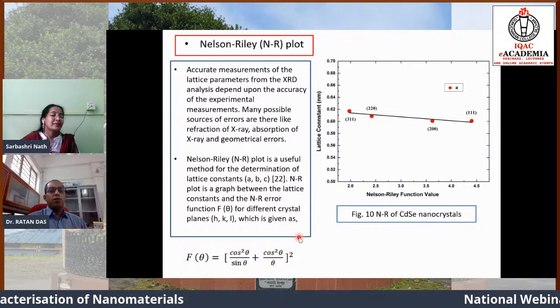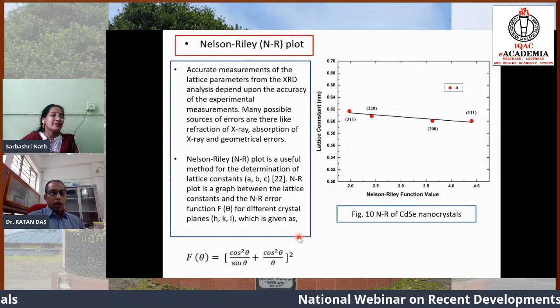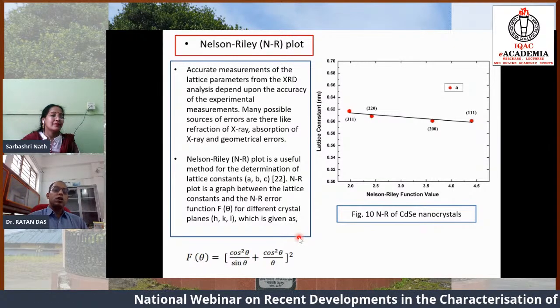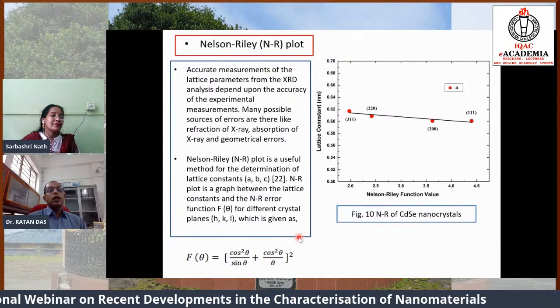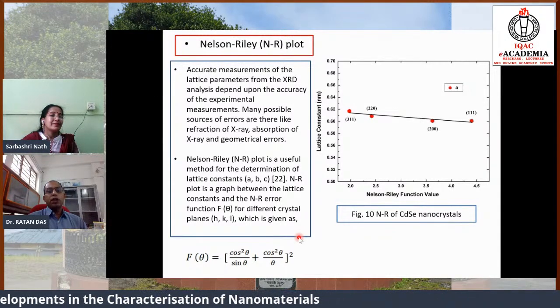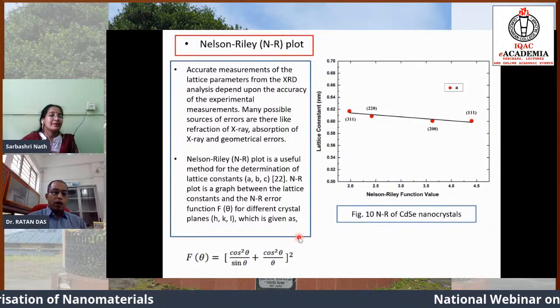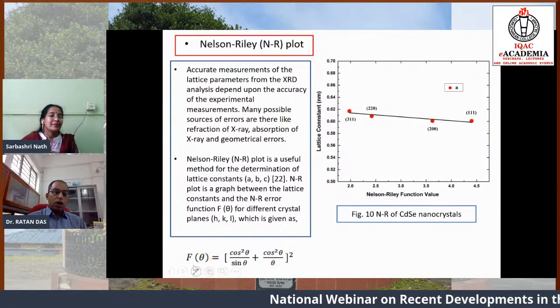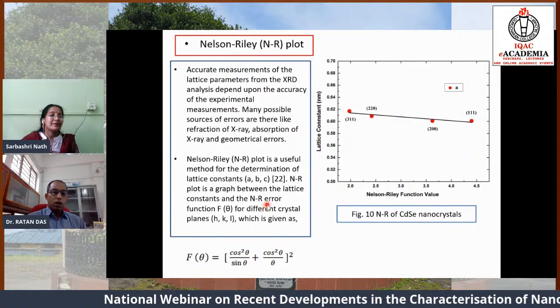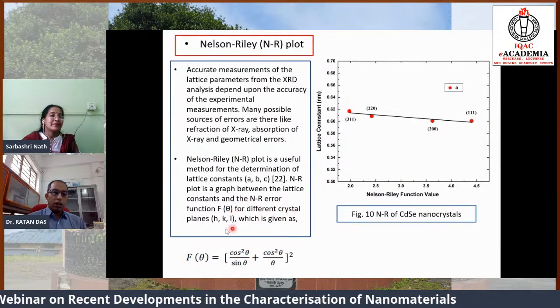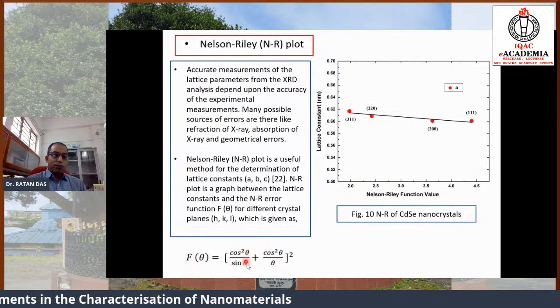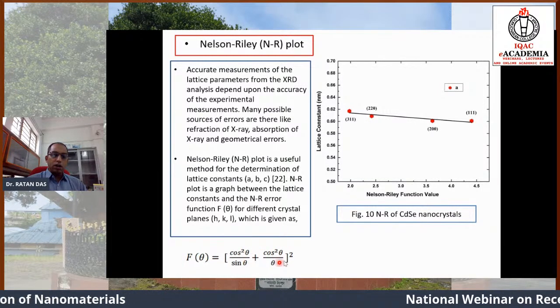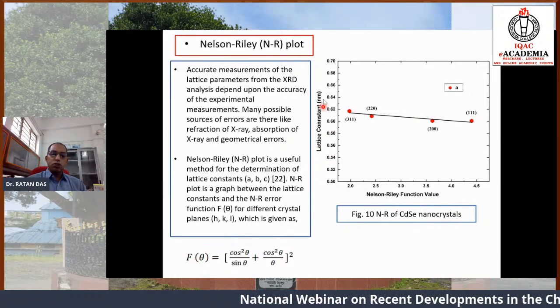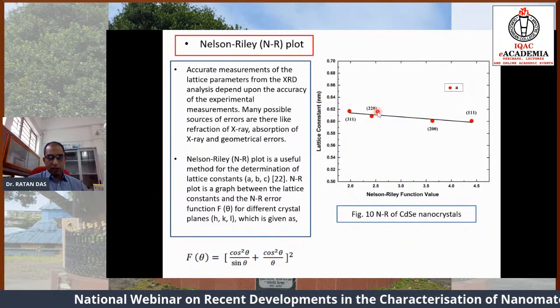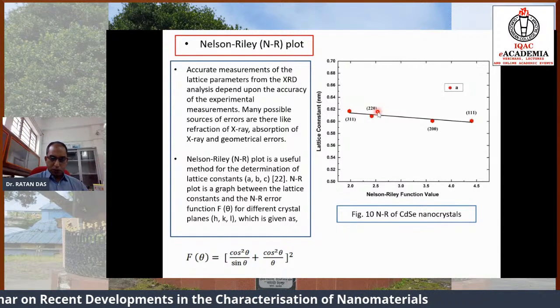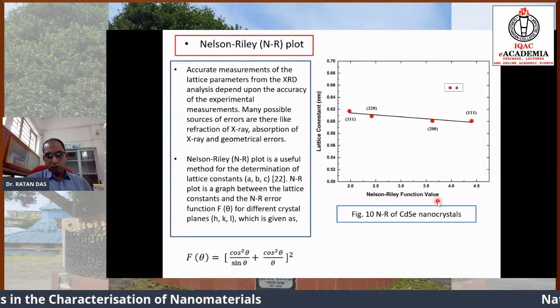That lattice constant can be obtained from the Nelson-Riley plot. In the Nelson-Riley plot, it is an errorless method of obtaining the lattice constant, where we use a particular error function, the Nelson-Riley error function f(theta), which relates to theta. We obtain the lattice constant value from Bragg's formula and the Nelson-Riley function.